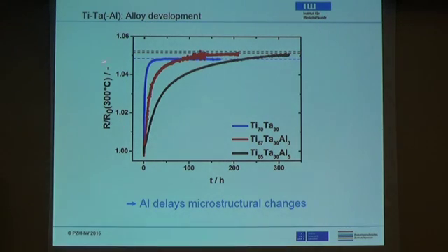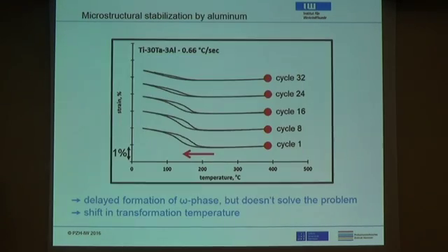This here is electrical resistivity data. It's normalized by the electrical resistivity at 300 degrees C. And if you take this titanium tantalum alloy, you see that upon aging, the resistivity quickly changes. And if you do change your composition with some aluminum, you see that this degradation process is delayed quite a bit. So aluminum additions do delay this microstructural change. This doesn't only work for the resistivity, it also works for the cycling.